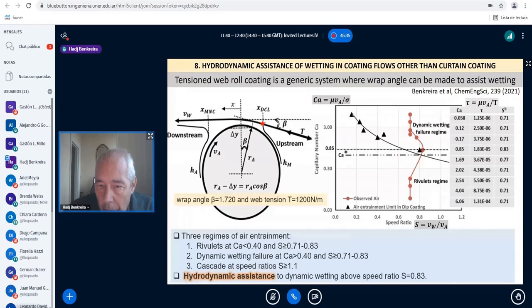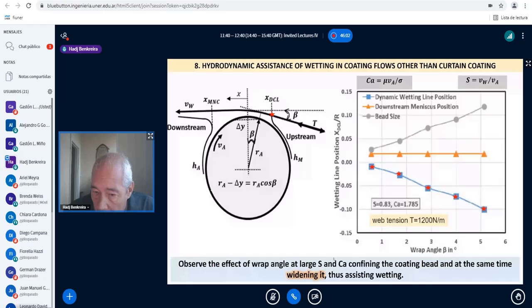And this is the line for the situation if you try to predict it using no hydrodynamic assistance, which is like in a dip coater. And this is the situation in here with playing with the angle, with the small wrap angle. And you see we are talking about in here a wrap angle of only a few degrees. And the same thing here, you see the wrap angle going from about 1 to about 5 degrees, and it causes the dynamic wetting line to move in here, and it causes the bead to be much more stable. So the hydrodynamic around the dynamic wetting line is very important in the assistance of wetting.